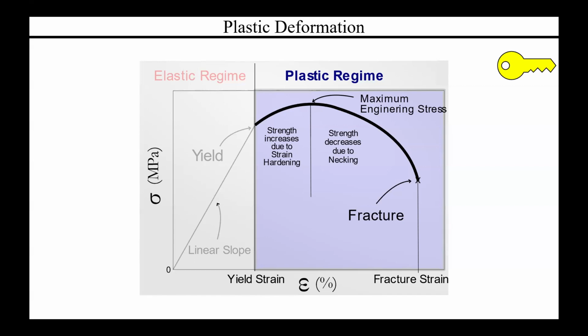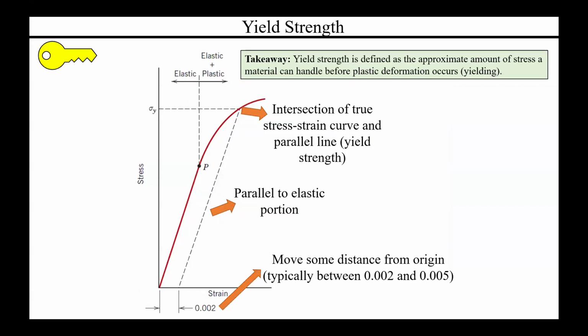So that's what I just said. At the beginning of the plastic region, the material is actually getting stronger. And then once you've reached that maximum stress that you can handle, the strength decreases, in part due to this localized deformation that is making the material, in principle, weaker. So the first important aspect of the plastic region is the yield strength. This is the stress required to facilitate plastic deformation. So in principle, again, you start off in your elastic region, that's your linear, and you may have this slightly elastic plus plastic buffer zone where there's a little bit of plastic deformation happening, but maybe some of it's recoverable, but not all of it. But then eventually you pass this point sigma y, or your yield strength, where anything past that point, there is no elastic deformation anymore. It is purely plastic.